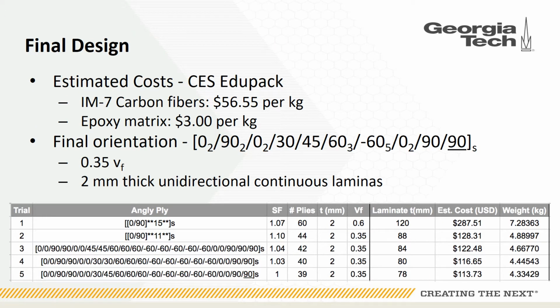For our final design, we found the estimated costs from CES EduPack. The IM7 carbon fibers cost $56.55 per kilogram, and the epoxy matrix cost $3 per kilogram. Using our final orientation with a 0.35 volume fraction and 2 millimeter thick unidirectional continuous laminas, we found our cost to have decreased from $287.51 to $113.73.